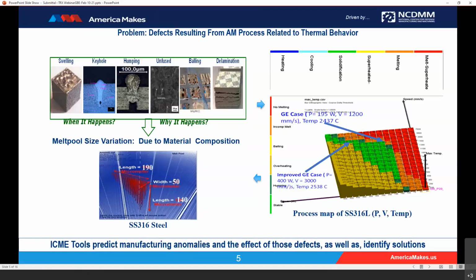The tool can be used to define a dynamic process map that relates balling, humping, keyhole, unfused powder, no melting, incomplete melting, overheating, to laser power and speed settings, or other critical parameters. That process map is shown on the right, and it shows the areas that are stable and unstable in terms of those process parameter settings. In the current example, the zones of stabilities and instabilities were validated for a single track of laser moving at different power and scan speed settings. ICME tools predict manufacturing anomalies and the effect of those defects, as well as identify solutions.